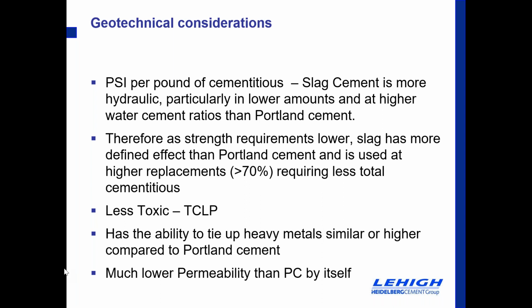The next point in geotechnical applications is that we're looking at the toxicity. Slag cement is less toxic as per TCLP data that we'll get into. Very important when we're looking at Superfund sites where we're using the cementitious material to capture heavy materials. So it does have the ability to tie up heavy metals, similar or higher compared to Portland cement. And of course, once it solidifies, has much lower permeability than PC by itself. So that when we do these job sites, we can then monitor the leachate coming out of the project and prove that we actually have contained the target material.